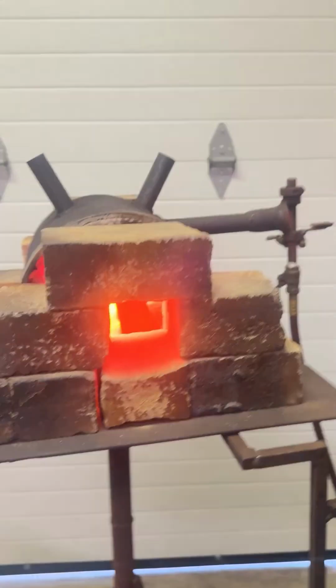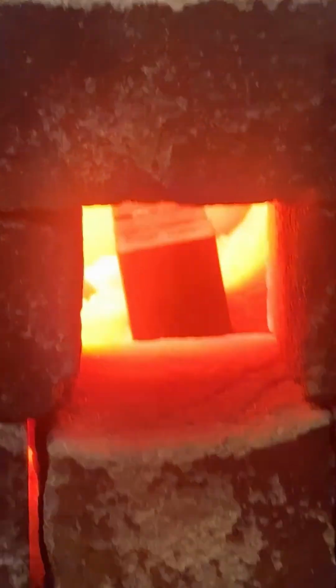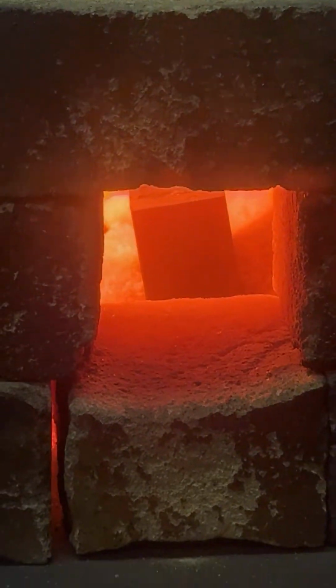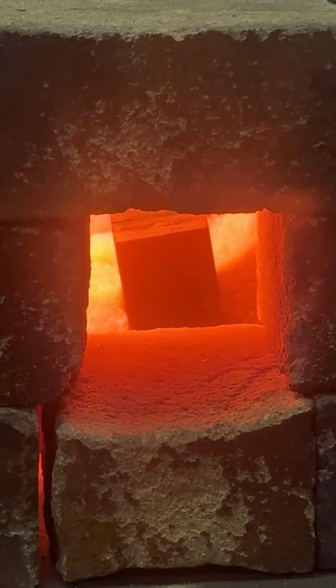When I was cutting all these tile pieces up, I labeled them all. Check this out. The steel is starting to glow incandescent. It's probably hitting 1100 degrees. You can still see part of the number 8. Oh, it just went away. I was seeing it while I was talking. I could still see the 8, and that steel is probably more like 1200 degrees. Anyways, I always think it's really interesting that you can see that ink up to such a high temperature.